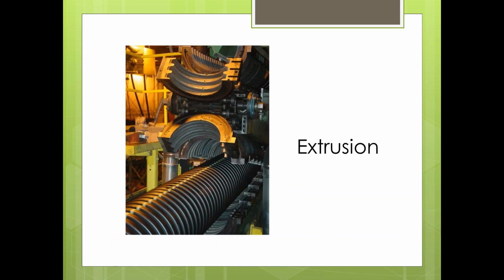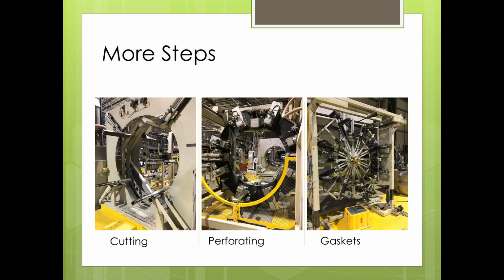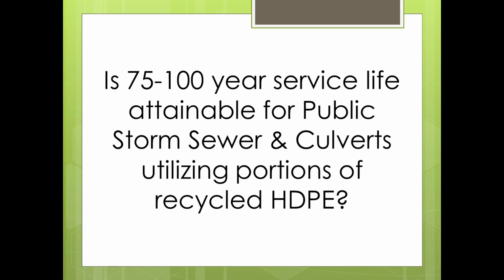So as those are all blended and then put into the hopper of the extruder, it gets melted, pushed through with an auger into the extruder and turned into pipe like you see here. Obviously, it can be modified from that point to be cut into various lengths of sticks of pipe, perforated for different applications, and you can apply things like gaskets at the end of the line as well.